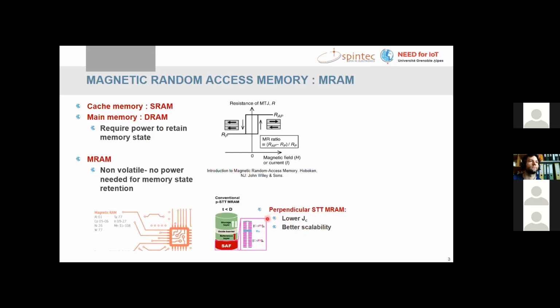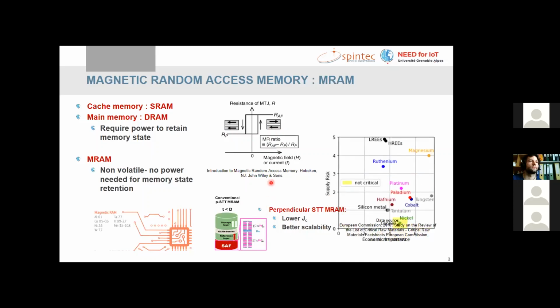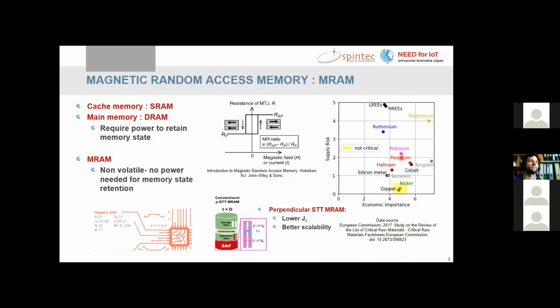A key point is to have a reference layer, which you can see here in the sketch, that is not switching, meaning that it has high thermal stability. This is mainly provided by the cobalt platinum multilayers that are grown below the reference layer. The only problem is that platinum is classified as a critical material by the European Union, and it has a certainly high supply risk.